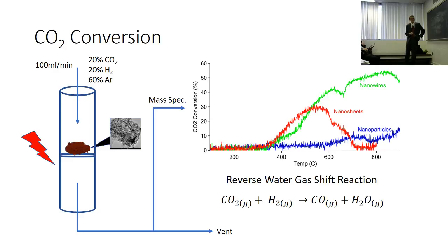Another thing to notice is that while the nanosheets peak out around 30% and then drop off at around 600 Celsius, the nanowires keep going. They have a little bit of a dip in the same place, but they get up to 55% at really high temperatures. It's really good.